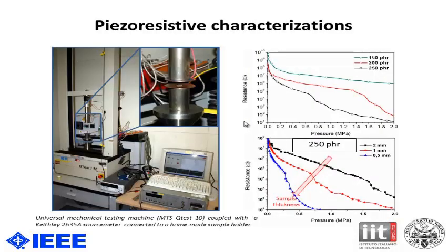The piezoresistive characterization was made using a universal mechanical testing machine connected with a source meter in order to measure the current related to a precise pressure applied. As you can see, we did the characterization varying the amount of filler, and the best results are obtained for 250 PHR, that means per 100 resin. So 250 parts of filler per 100 parts of resin. So we decided we will use the 250 PHR composite.